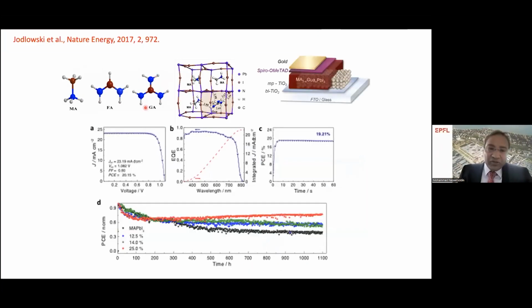Since you cannot form pure three-dimensional perovskite using guanidinium because it's a larger size, what we have come up with is, can we combine a larger cation to some extent and a smaller cation in a mixture at a ratio of 3 to 1? So 75% is methylammonium cation, 25% is guanidinium. As you can see, these are critical simulations.